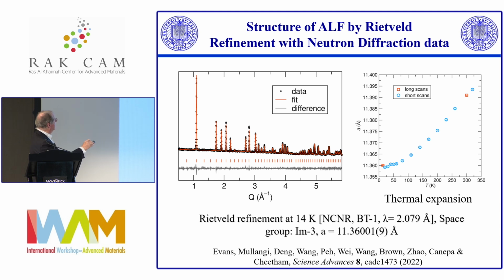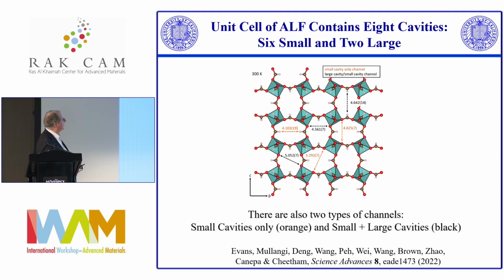This is just the lowest temperature, and this is just the lattice parameter changing as the lattice gradually expands. Down at very low temperatures, it shows essentially zero thermal expansion for about 50 degrees before it starts to take off. So there's absolutely nothing in the cavities. The structure looks like this.